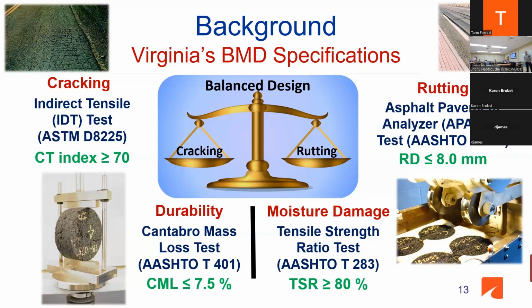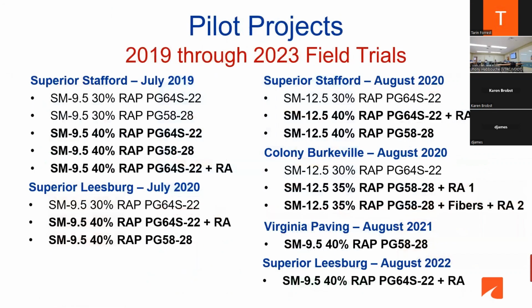We also look at durability. That's the Cantabro mass loss test, maximum 7.5%. And we want to make sure that we're not jeopardizing moisture damage. That's also critical for Virginia. We look at a tensile strength ratio, a minimum of 80%. That's typical, and it hasn't been changed in a while for Virginia. So that's our framework. It balances between cracking and rutting, giving you a good recipe, a good performing mix.